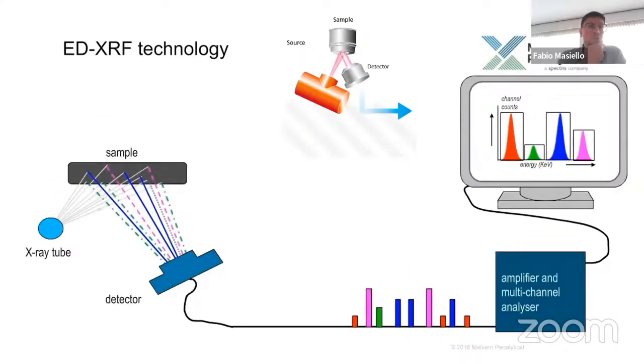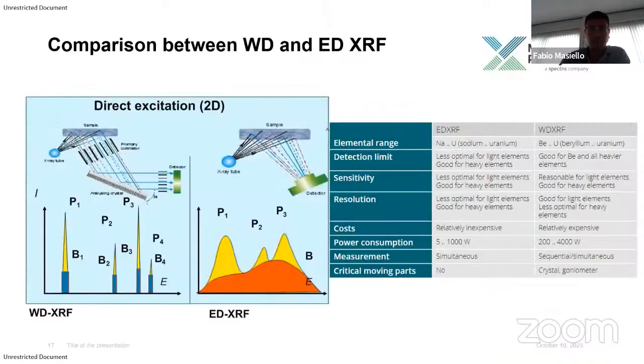The other technology used is the so-called energy dispersive X-ray technology. You see that the setup is simpler. There are no moving parts. In this case, what is used is the very high energy resolution of the detector. Again, the sample is irradiated with a white, polychromatic X-ray beam, and the signal is recorded by an intelligent detector, an SSD type for example, with high energy resolution, which allows you to see in one shot all the different characteristic lines in your sample.